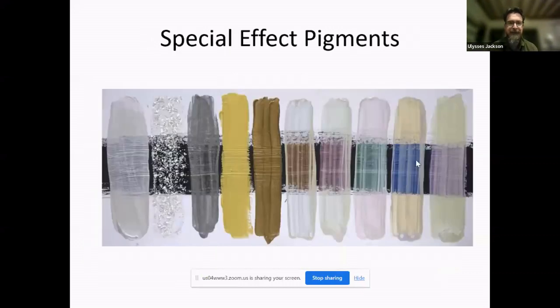In oil paint, all of these would wet out very easily and similarly. In water-based paint, the inorganics do wet out very easily because they have oxygen and sulfur groups on the outside that like water, but they might be more difficult to stabilize because something like yellow iron oxide or Viridian green have their own challenges. Viridian green wouldn't be stable in a high pH environment, and yellow iron oxide doesn't play nice with other ingredients, and it wants to make your paint kind of jelly-like.